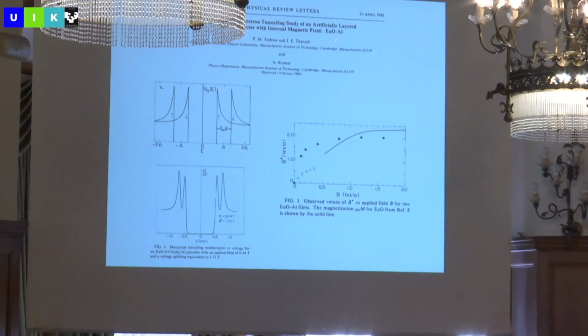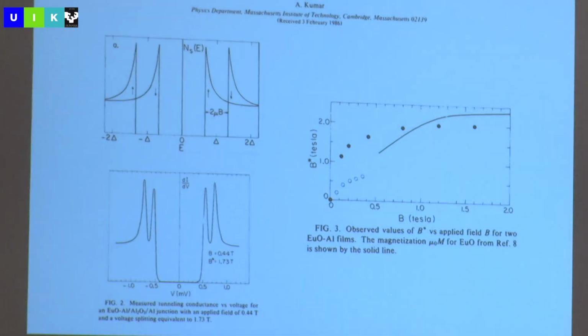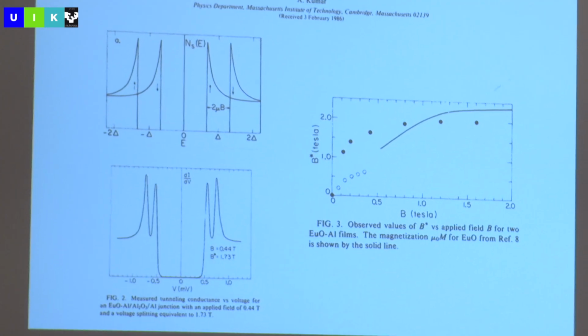And again, it's an old problem, and I'm only wanting to show you these slides to give you a sense that even back in the 1980s, people were already doing things like putting ferromagnetic insulators, in this case europium oxide, on superconducting aluminum, and seeing things like split density of states. Now remember, it's an insulator. You're putting an insulator on top of a superconductor. So you might think, well, it's not going to do anything. It's an insulator. But the scattering, even just those first few atoms, when it would scatter off of the insulator, was enough to dramatically split the density of states in the superconductor.